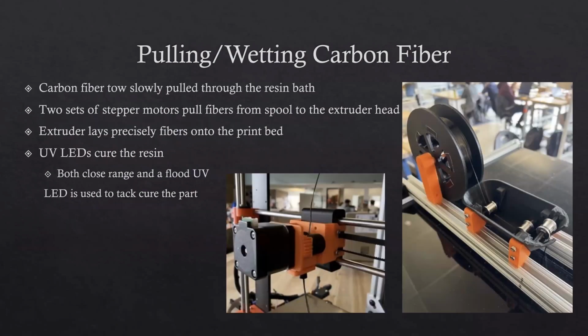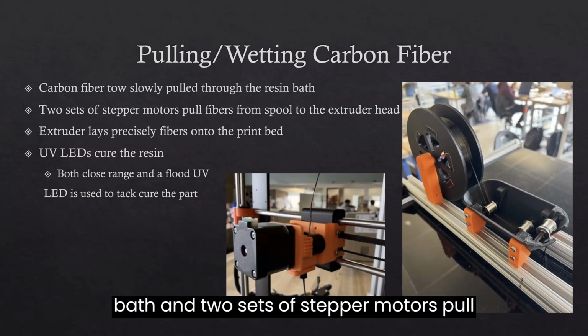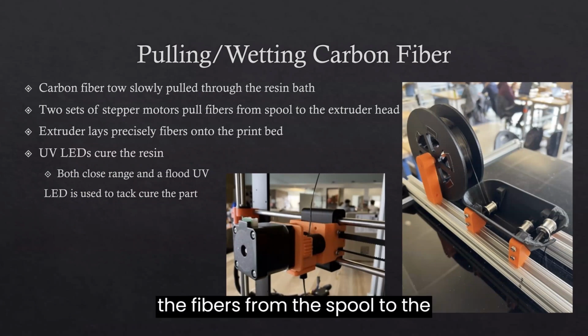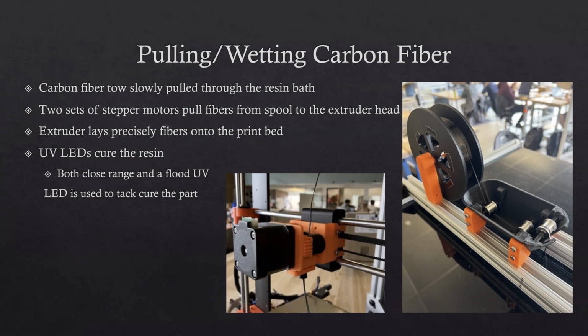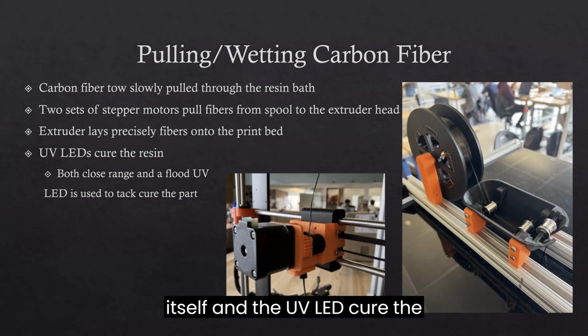So this is our pulling and wetting system for our carbon fiber. Carbon fiber tow is slowly pulled through the resin bath, and two sets of stepper motors pull the fibers from the spool to the extruder head. Extruder lays precisely fibers onto the print bed itself, and the UV LED cure the resin for tack cure, and the oven for cure.